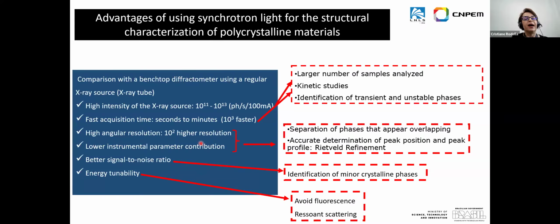But you have another advantage, which is high resolution. And with this possibility of using high resolution methodology, we can identify and separate crystalline phases that are overlapping in your diffractogram. And we have an accurate determination of peak position and peak profile that will be very important to quantitative structural analysis that you can perform using Rietveld refinement.